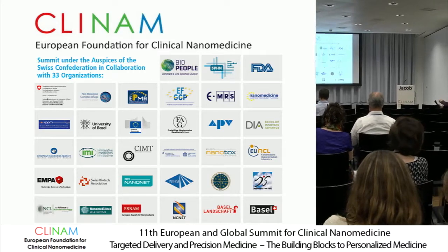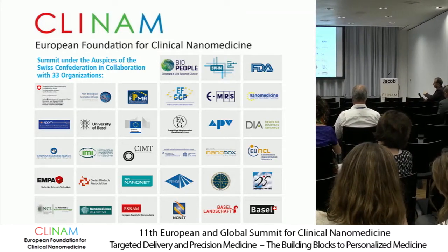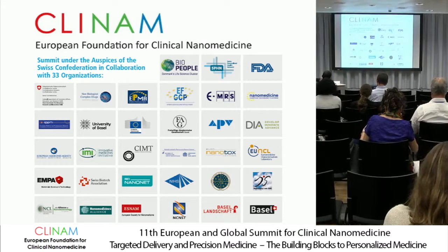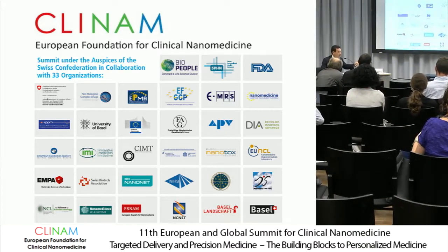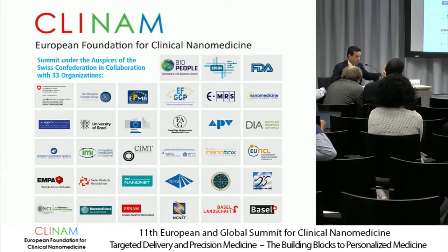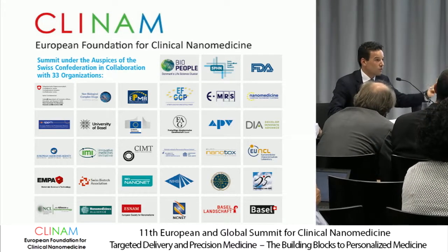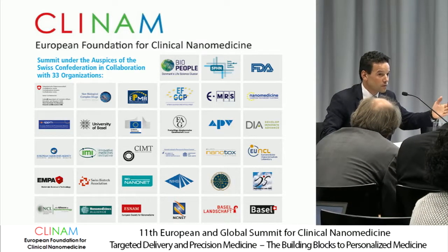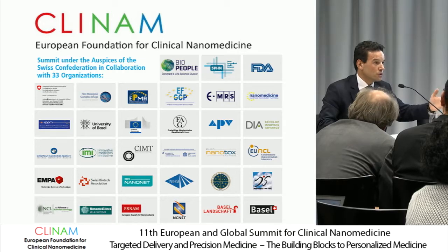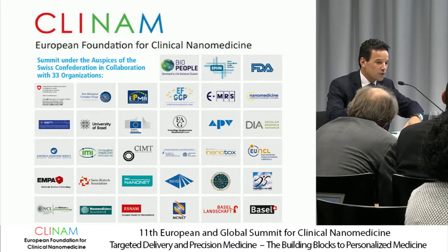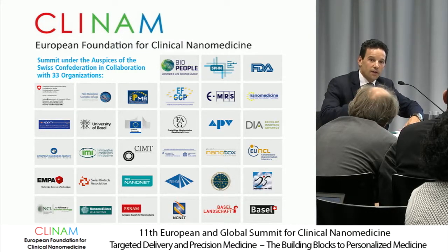That's where they come in with not accepting any longer one single measurement. They want to have at least one volume, which could be an electron microscopy technique, a dynamic measurement, and if it's necessary, they want to have a third, which could be either a fractionation system or it could be electrophoretic or a surface charge. Depending on the outcome and the biological outcome that the product is designed for, they come back by asking this. And I think, speaking from the EUNCL perspective, for the cases that we've seen, we analyzed more than 30 cases under our process.